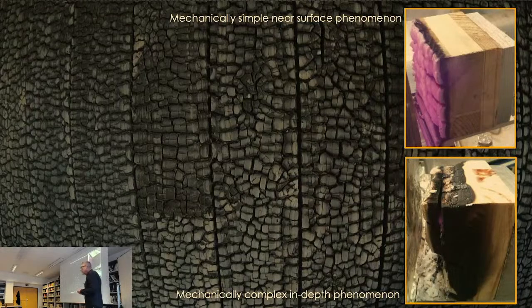So now, can you circumvent all this complexity? Yes, you can, if you guarantee that self-extinction happens very fast. You can see the beautiful pattern of charring. When you get this perfectly homogeneous, extraordinarily well length-scaled pattern, it is because you have a single characteristic length scale, which is a very thin char. If you have a very thin char, the cracking, everything becomes a very homogeneous pattern. It protects heat transfer into the solid, so none of this other shrinkage and deformations and splitting and moisture happens. If you wait until this happens, everything comes your way.